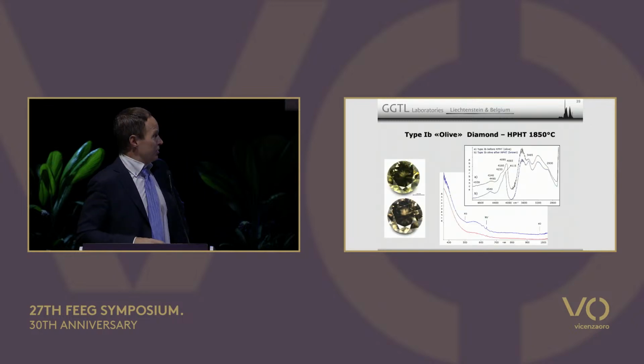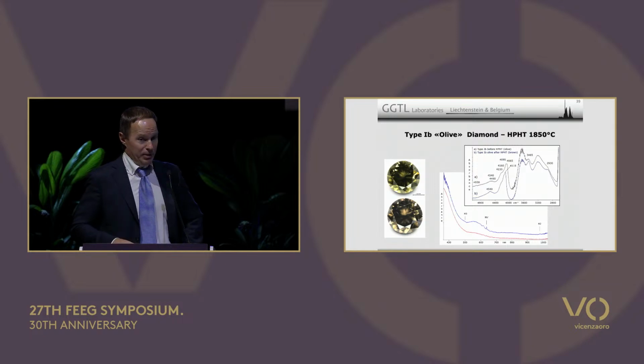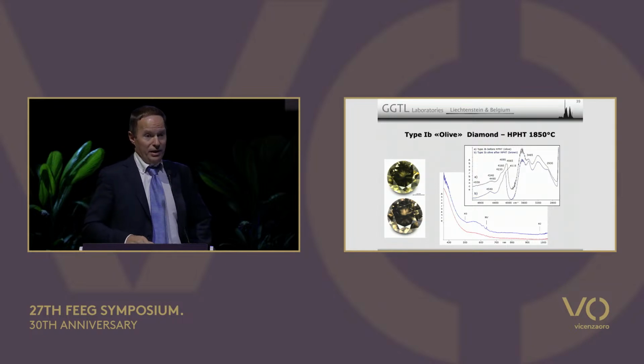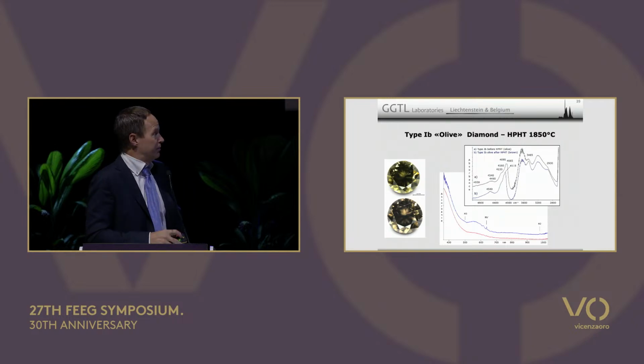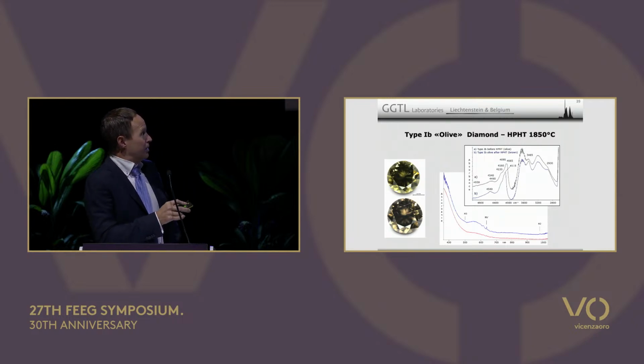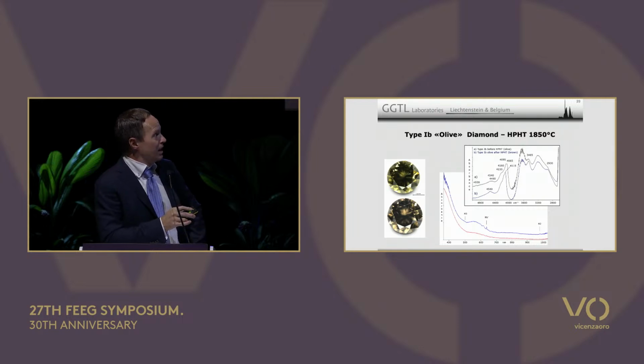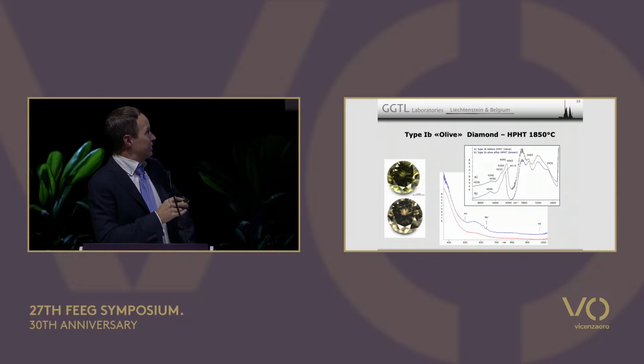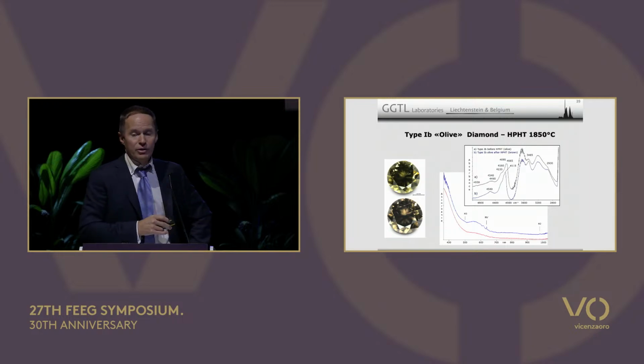Looking at the spectroscopy of samples and doing some HPHT treatment experiments showed that it's exactly the same reason as what I showed before. Prior to heat treatment, you have this spectrum here, with a strong 4065. After heat treatment, the 4065 disappears, and you form 4115 instead. The spectroscopy changes from this to that, and the stone changes from olive to brown. So the type 1bs did exactly the same as our type 1a samples.